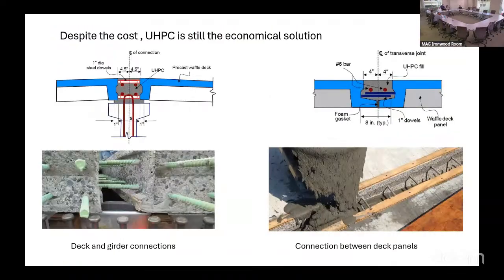Next one. This is the UHPC project. Maricopa Department of Transportation had to replace several bridges, but the budget that they had was only for one bridge because of the cost of replacing the bridge. So what we proposed is to use UHPC. This is ultra high performance concrete, which has about 3 times the fiber content that is in the project that we use for track slab. It has about 2% steel fibers and a lot of superplasticizer.